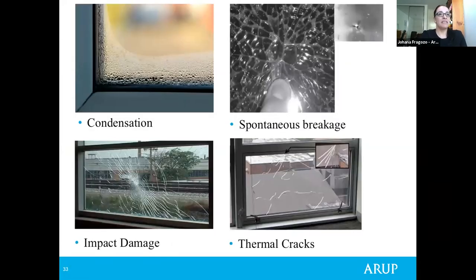Some of the typical defects that we encounter with glass: condensation in double glazed units, which is the buildup of moisture inside the unit because of temperature changes or fluctuations of moisture in the exterior and the interior, through air ingress through discontinuities of the perimeter seal. Then thermal stress, which is created when one area of the glass pane gets hotter than the adjacent areas. This is becoming a problem at the moment because of the wide use of sunshade structures.